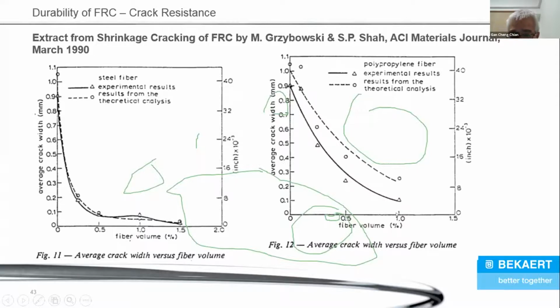If you use 1% fiber volume, 1% is 9.1 kilograms of polypropylene fibers or polymer fiber, and bring the curve up, you will find that it also achieves a crack width of 0.1 millimeter. So both types of fiber can achieve 0.1 millimeter crack width. It's no problem at all. In fact, we don't even need 0.1 millimeter. We are actually specifying 0.2 or 0.3 millimeter, but you can actually achieve as small as 0.1 millimeter.